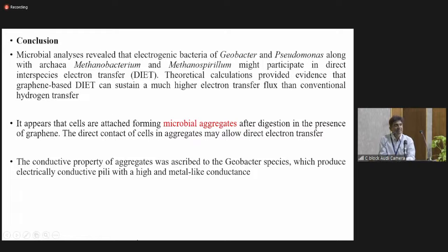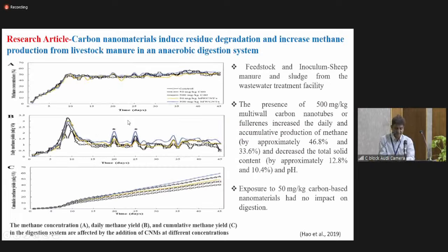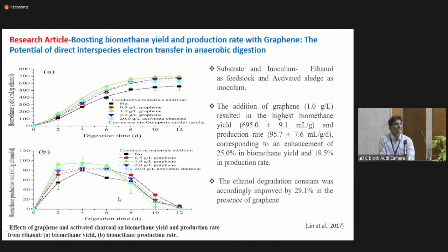Again, in this study you can see it is only effective at 1 gram of graphene. If we take 2 grams of graphene, it is reduced or has no effect on the biogas enhancement capacity.